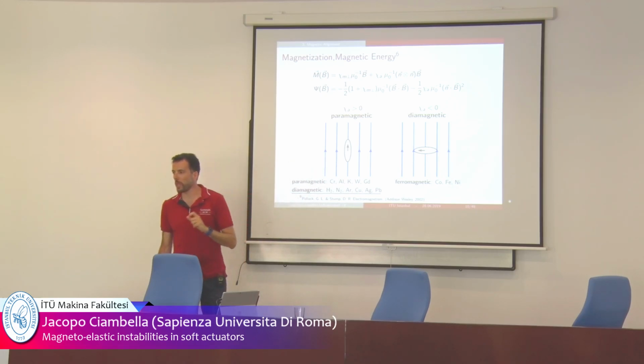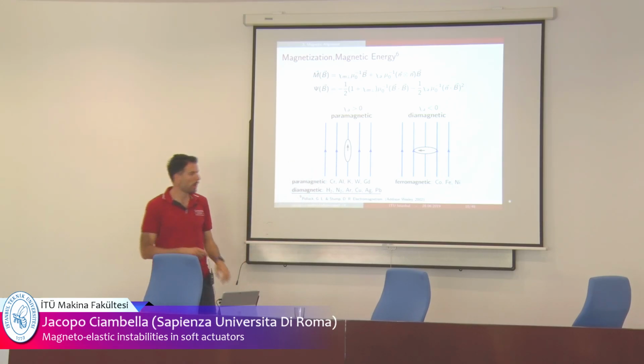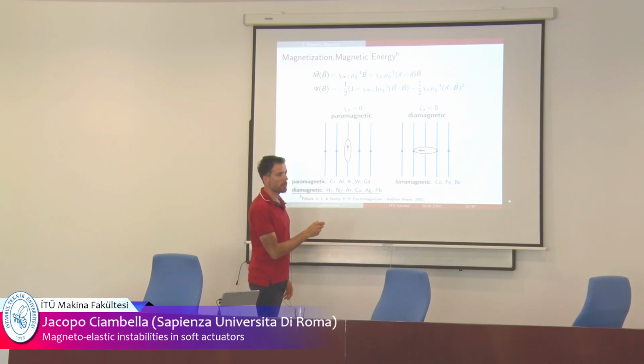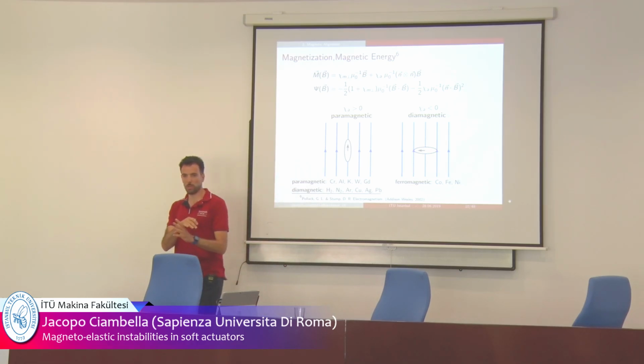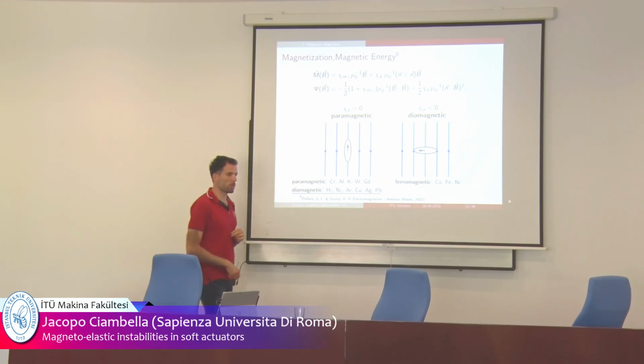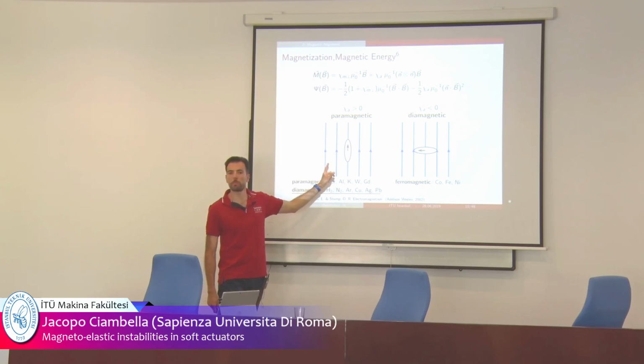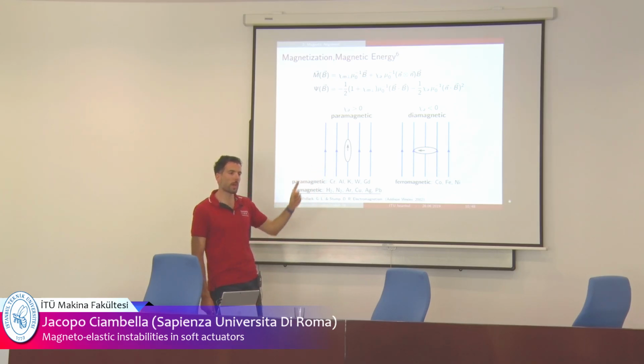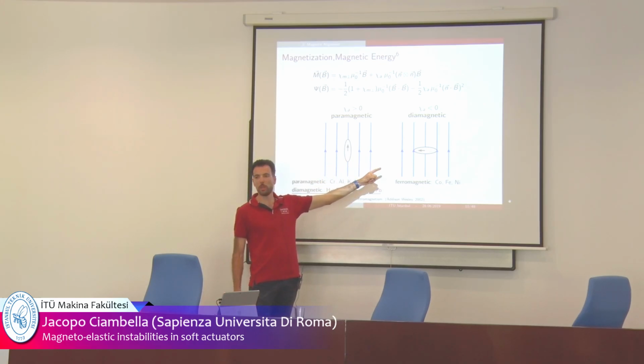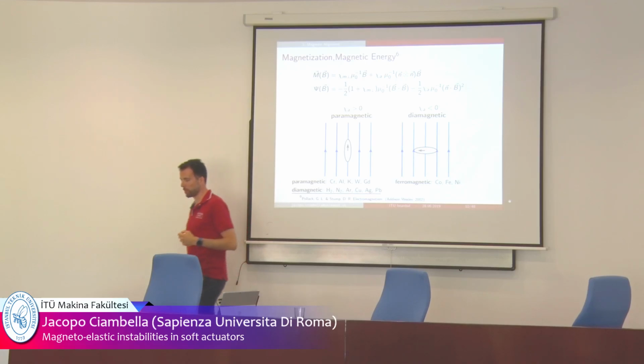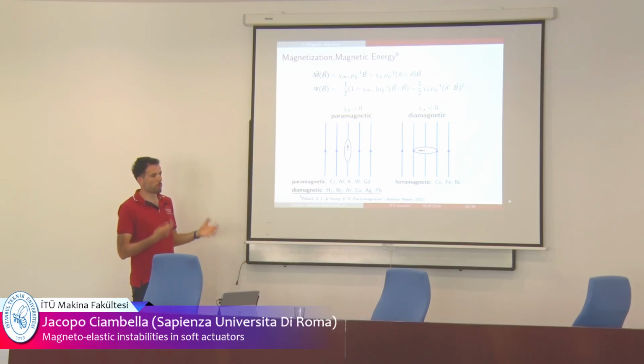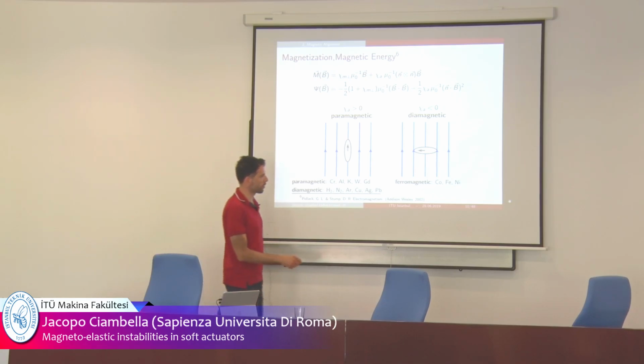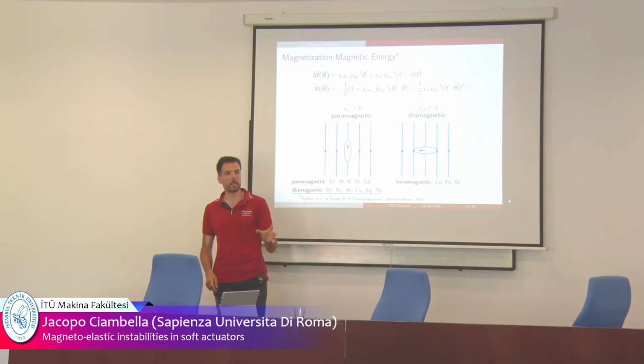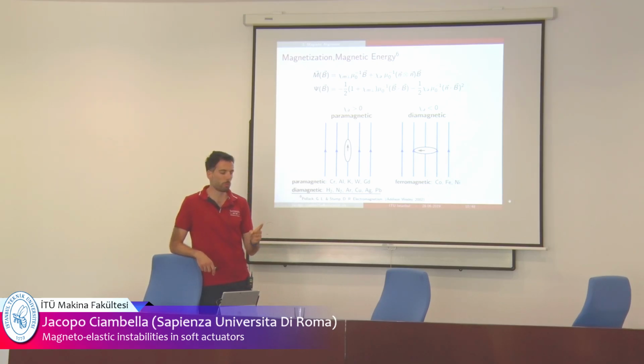On the opposite, if chi is negative, the material is called diamagnetic, and because of this minus sign, the energy is minimum when the particle and the magnetic field are orthogonal. The fibers we use are mostly paramagnetic fibers, so they will orient parallel. But in principle, you can have a mixture where you use both paramagnetic and diamagnetic, so some of them will orient perpendicularly and some of them parallel to the field. Then you have more complex situations with ferromagnetic material. I didn't talk about ferromagnetic material, but for it the relationship is much more complex because the relationship between magnetic induction and magnetization is highly nonlinear.